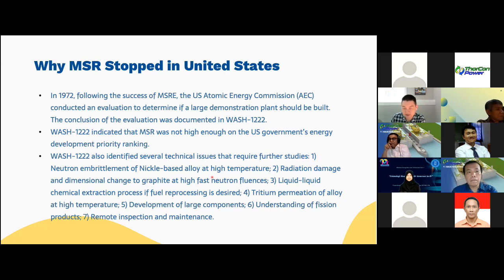And the fifth one is development of large components. The MSRE is using a special nickel-based alloy. It's relatively small because it only has 8 megawatts. If you want a larger demonstration power plant, you will need larger nickel-based alloy components, which were not available at that time. And also the understanding of fission products, which is really about the release of cesium and iodine and other important elements. And also remote inspection and maintenance. If you want these power plants to continue to operate for 30, 40 years, you would definitely need to do some inspection and maintenance, for which you have to develop a robotic method to do that work.